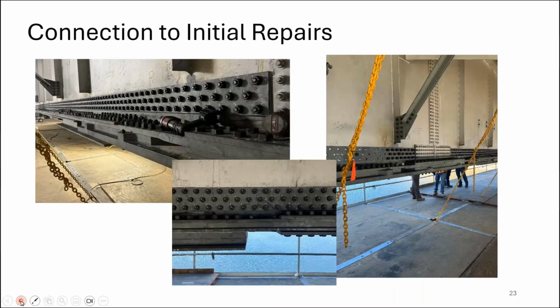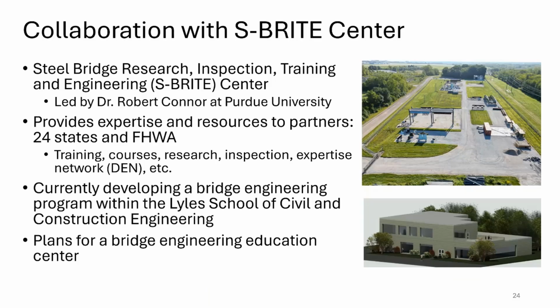And this is a good comparison of what the difference between that material really meant to this bridge. This is the critical repairs that were done with 50 KSI steel. And then on this side, we have the repairs that were done with the permanent, with the 100 KSI steel. So we were able to remove quite a bit of weight from the structure. And with that, I will turn it over to Francisco to get into the details of the web crack arrest plate. So, well, thank you, Keeling.